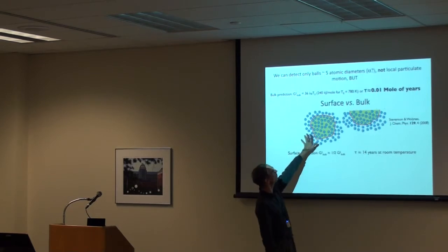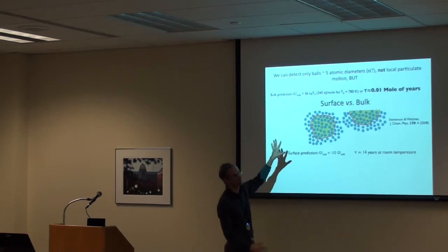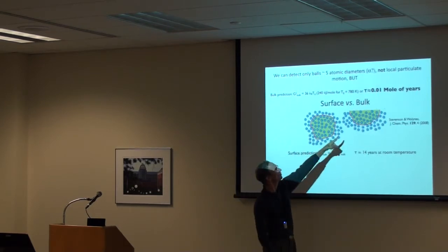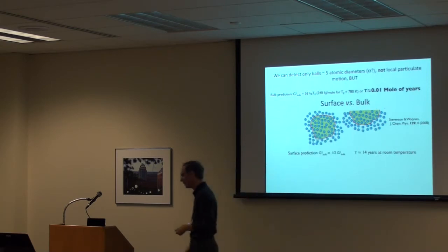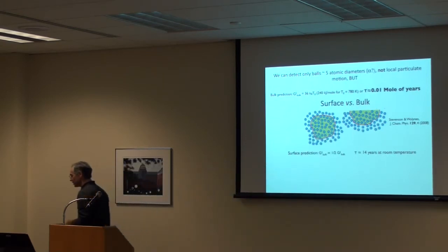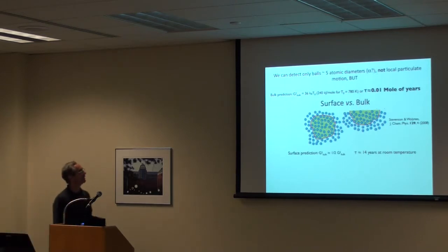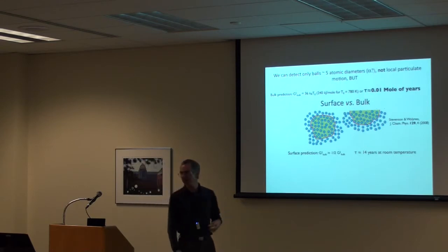Well, it turns out that same theory, through some very clever and simple derivations, actually predicts that if you have this thing on a surface instead of having it sit in the bulk, the activation energy actually depends on the surface area that's in contact with the surroundings, and you're halving that surface area, and so the barrier should go down by a factor of 2. So instead of getting a 36 kT barrier, it would be an 18 kT barrier. Okay.